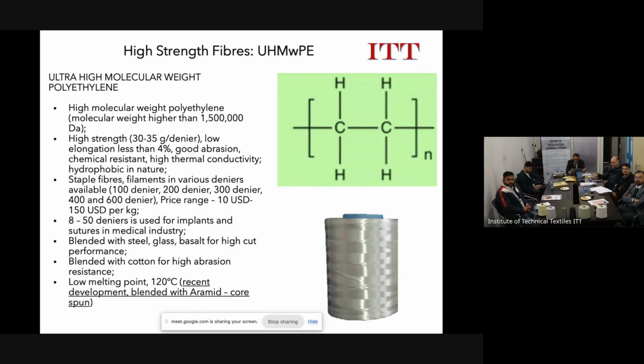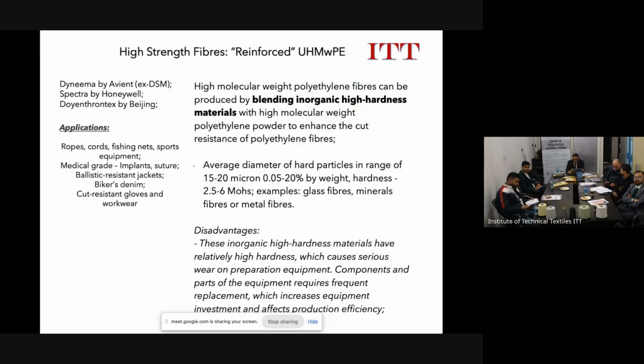We are even working with black color, dope dyed. Abrasion resistance is very high. One of the major challenges with this fiber is the melting point. At 100, 120, it starts degrading. For that reason, we really need to be very careful which product and which end customer we are targeting with this material. One of the developments we are doing uses a core spinning technique, where we put HPP fibers or ultra high molecular weight fibers in the core and aramid in the sheath, so that the exposure to fire comes to aramid first and HPP is hidden inside to provide the high strength properties.